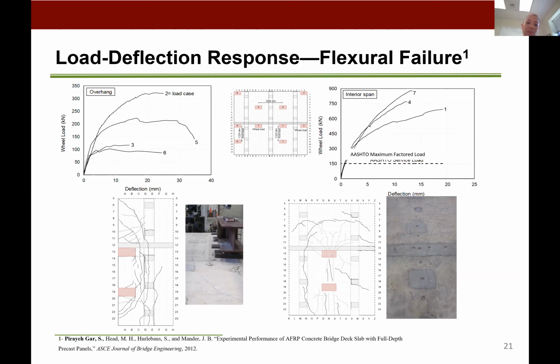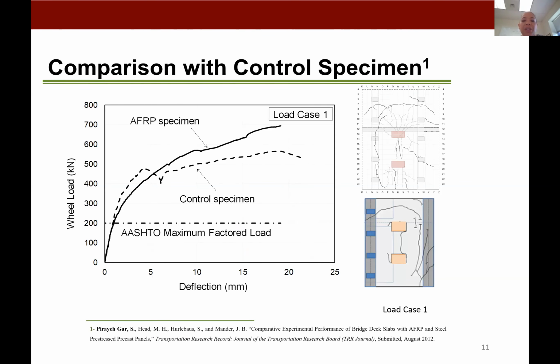So we saw this nice fan behavior. While the bars don't yield, we were able to come up with essentially a modified yield line theory, and we got nice continuity just from mapping the cracks across the seam or the joint there, which is very assuring. And then we were able to achieve some nice load deflection curves. This is both when we had it on load case 5, when we were loading on the overhang, as well as on the interior. We were able to achieve or exceed the AASHTO minimum factored load and service load. So specifically, if we zoom in on load case 1 on the interior span, what did we learn?